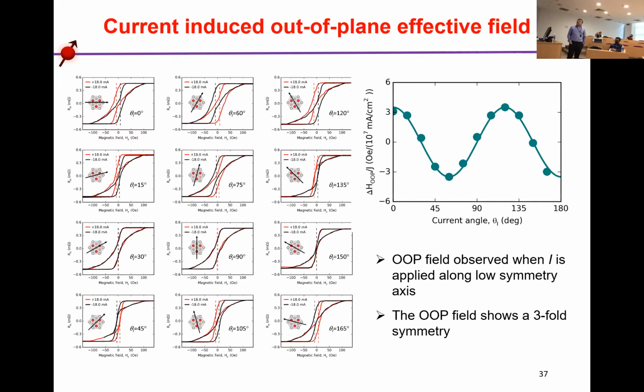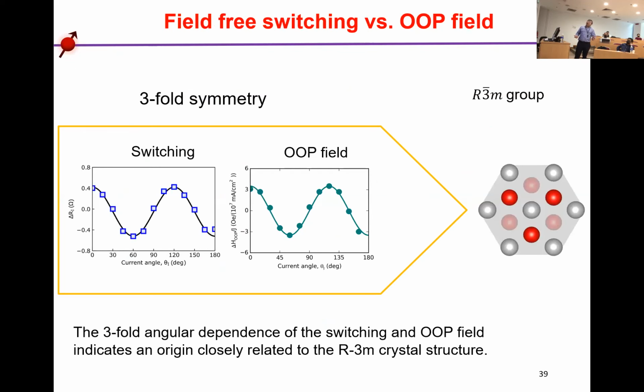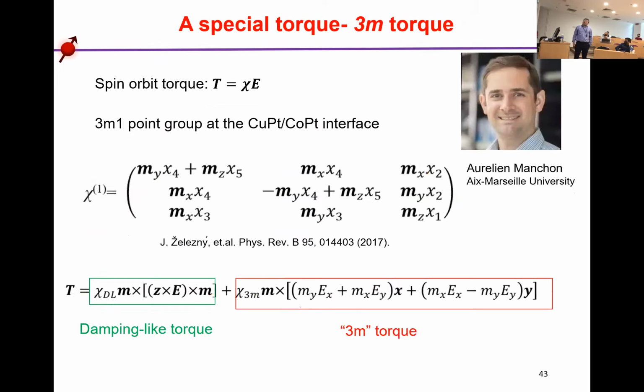In one word, we can say this switching follows the threefold symmetry. Definitely, we can also evaluate the out-of-plane torque and out-of-plane effective fields, which also follow the threefold symmetry, the same as the crystal structure.